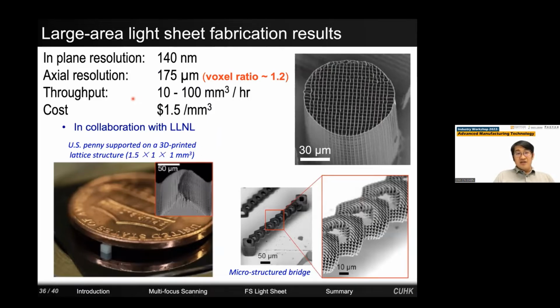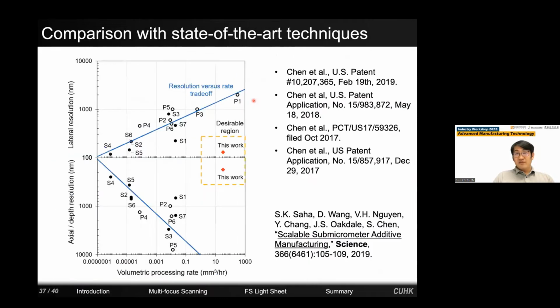And also the cost is reduced by around 95%, and the throughput is now roughly 100 cubic millimeter per hour versus originally 0.1 cubic millimeter per hour. Okay. As a result, this work was published in the Science magazine.